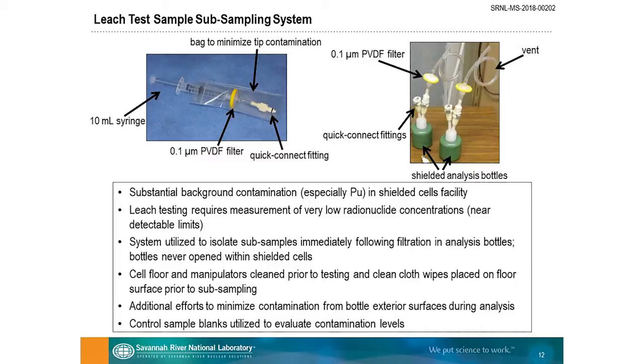So this is what we did. We used syringes with a filter on the end. We would pull a sample out of those vessels, put it directly in a syringe, attach this to a sample bottle with these quick connects, so that once this is filtered, it goes directly into a sample bottle that is vented with a filter on the downstream side, because plutonium has the characteristic that it will almost crawl over every surface inside that cell. So we had to really isolate it on both sides, upstream and downstream.